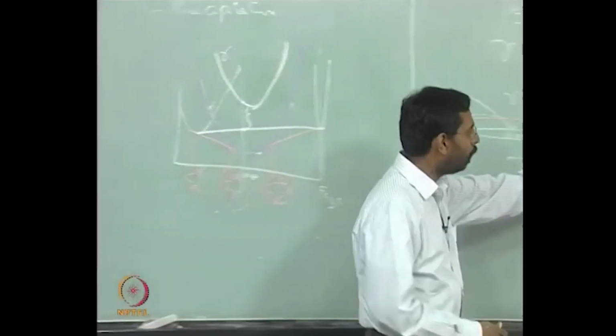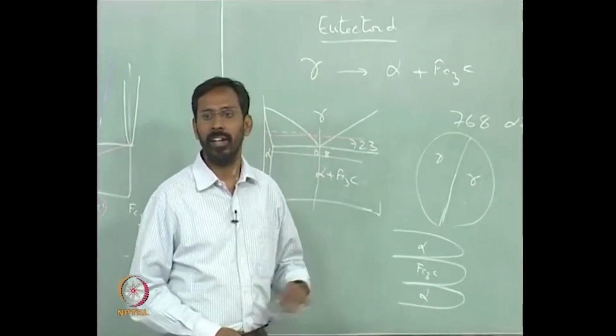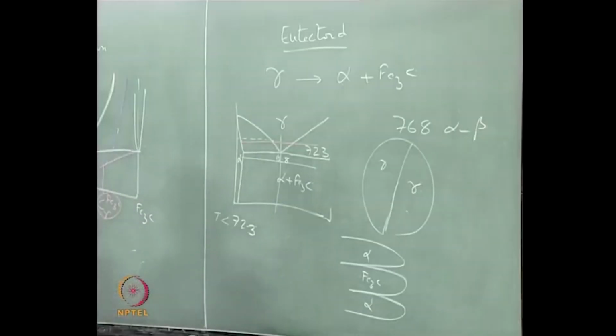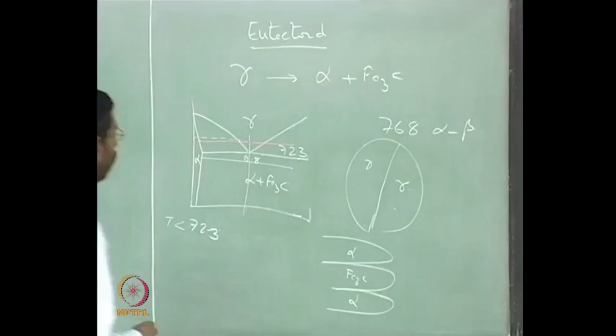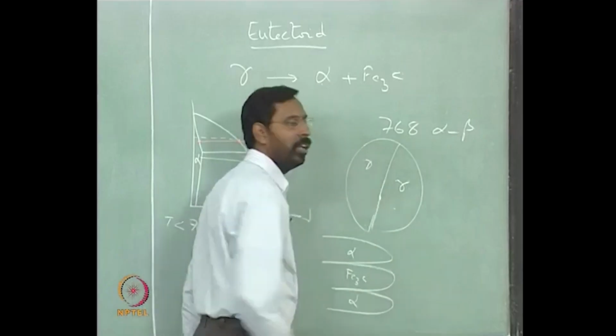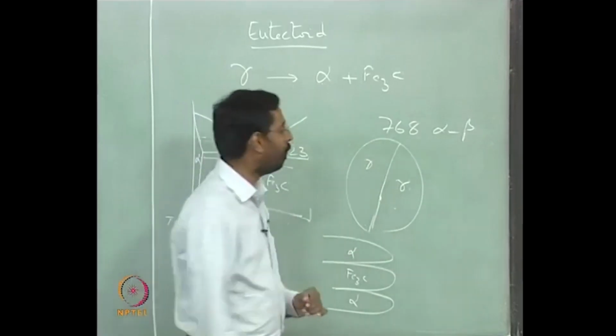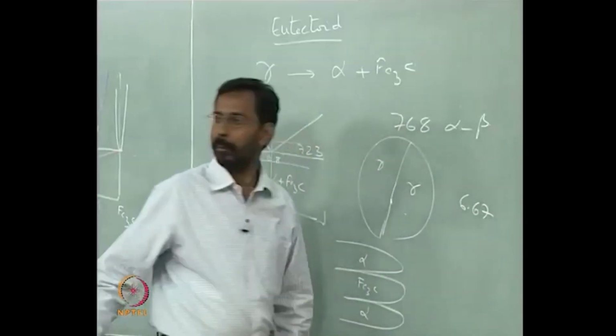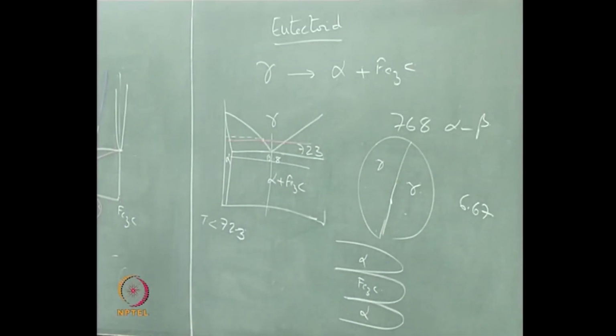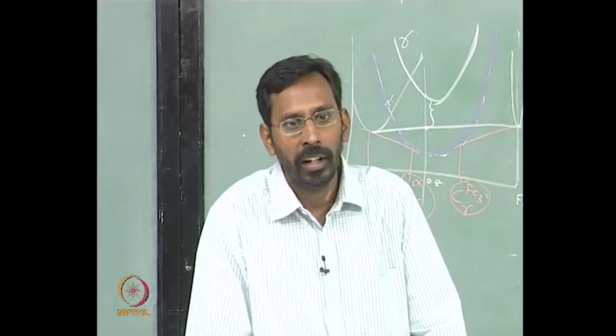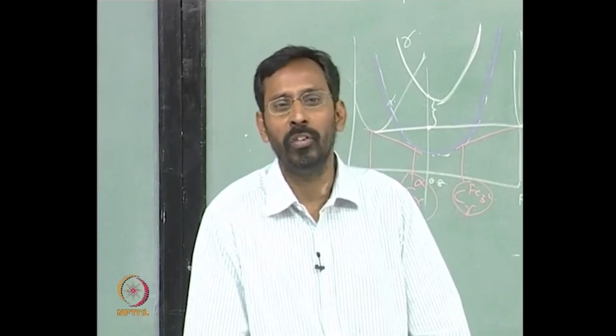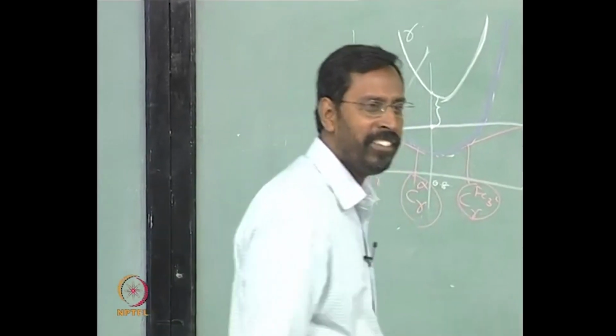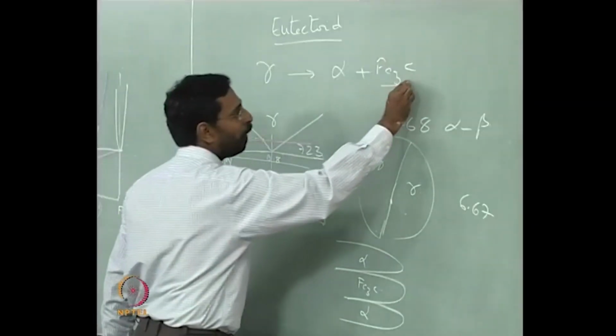That is where we say the moment you have a gamma interface at the grain boundary, the atoms at that temperature have a chance to move, because the temperature is high enough for the atoms to move, and the moment in a small region you see the carbon atoms coming to a level of 6.67% by weight, and in terms of atomic percent it is how much? 20? Why are you so doubtful? It is 25. Fe3C, very easy, 3 atoms of iron, 1 atom of carbon.